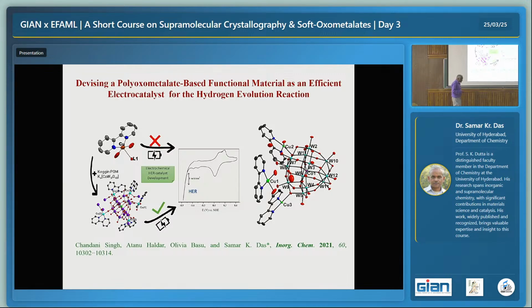This is the idea. Now one may argue with me that maybe I'm getting elemental copper, maybe the compound gets decomposed, the copper(II) becoming copper(0), and copper(0) is a good catalyst for hydrogen evolution. Everybody knows that. But then we did a lot of control experiments. After electrolysis, we checked that material and we found no elemental copper. We always find copper(II) only. So copper(I) forms in a very unstable manner, very active, and immediately reduces the proton to hydrogen. That's why at any resting time, if you do XPS, everything you get is copper(II). So in a similar system, when you put them in a coordinate covalent bond, you get continuous hydrogen evolution, a very stable catalyst. So the intrinsic nature of the metal makes this difference.